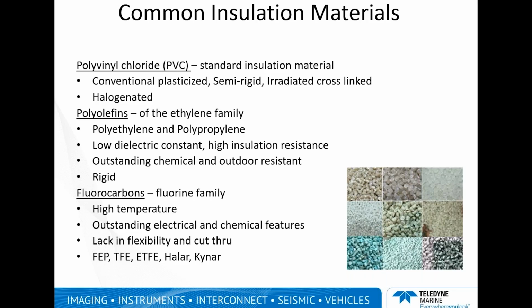The next material is the fluorine family. It's going to be Teflons, which will be FEP, TFE, ETFE. Again, great chemical resistances, very low dielectric constants. When you look at the dielectric constant between polyolefin or polyethylene and Teflons, Teflon has about a 2.10 dielectric constant. Your polyolefins will range at about 2.23. What this means is with that slightly lower dielectric, you're able to get a little bit smaller profile in your pairs and your coaxes, which could mean the difference between being within a specification or being slightly out. So definitely you've got some alternatives there when you're looking at these two materials.